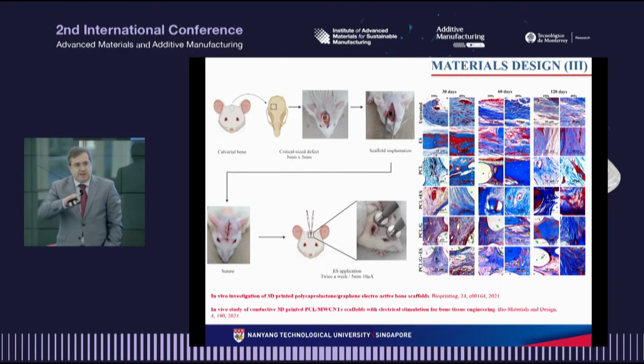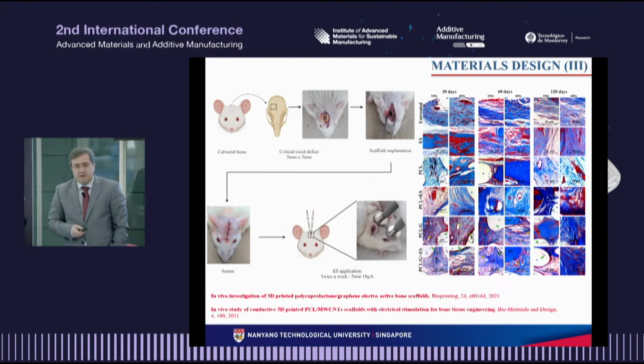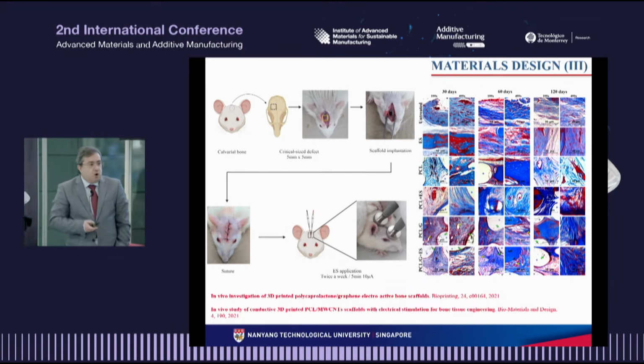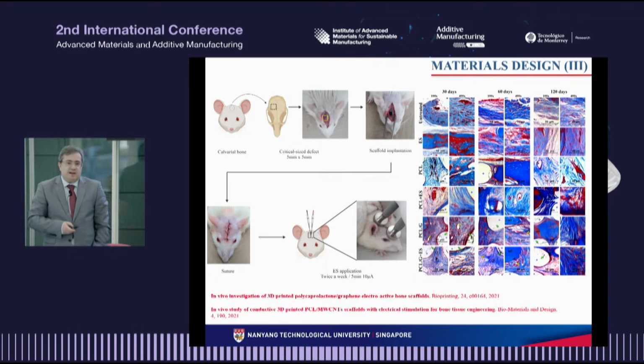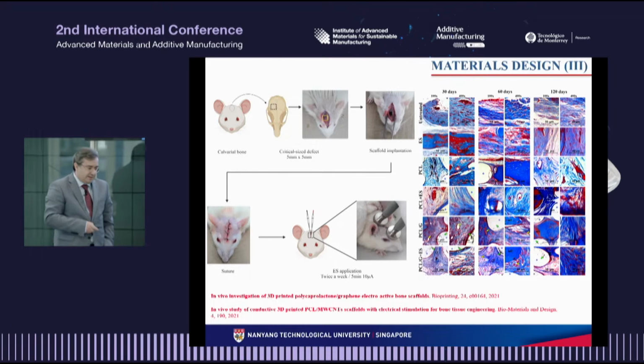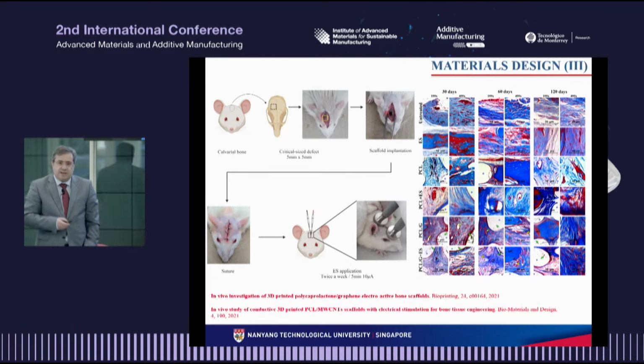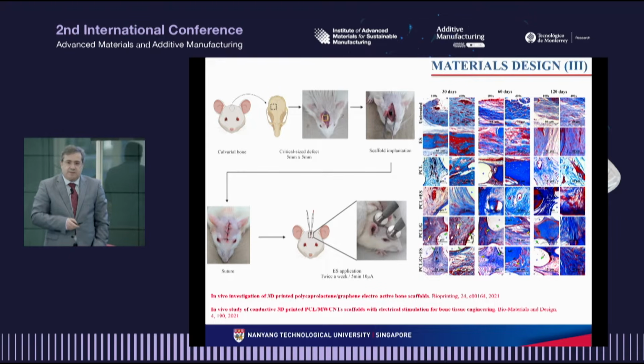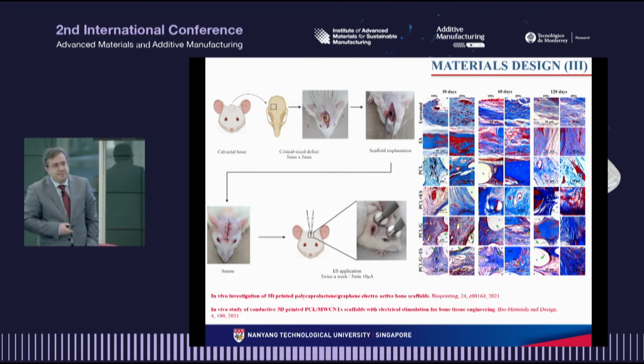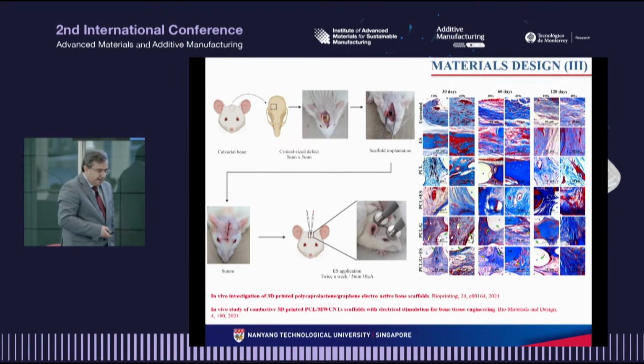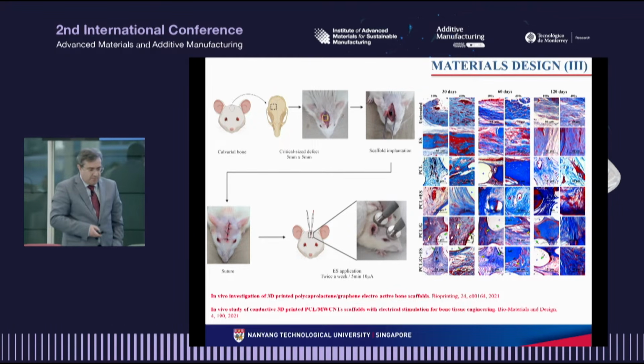We created critical size defects in the calvaria of rats, and we used our electroactive scaffolds and compared the performance of our electroactive scaffolds with non-conductive scaffolds, using or not an external electrical stimulation. And what we observed was that by combining the use of these electroactive scaffolds and external stimulation, it was possible to accelerate angiogenesis, so the formation of the vascular system, and mineralization, obtaining a more organized bone.